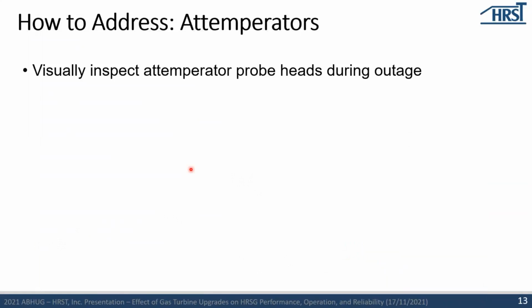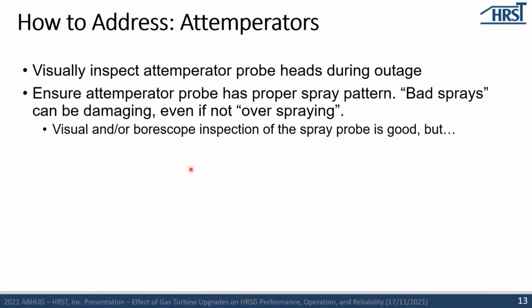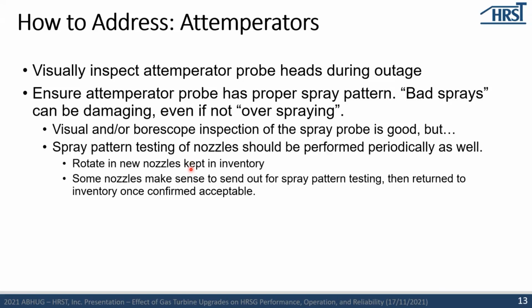So aside from just changing out attemperators, it's always good to perform visual inspections of the attemperator probe heads, because even though you may not be overspraying, that doesn't necessarily mean that there's no issue occurring within the spray water probe itself. If it's stuck open or if it has an improper spray, it could be releasing liquid water into the system that's not evaporating, and this can quench tubes or even cause cracking on the downstream piping as well. So it's important to do spray pattern testing of the nozzles periodically. You can rotate your nozzles in and out of inventory, so you always have a stock of good refurbished nozzles. And then you can plan to send out the other ones for testing and be returned for the next outage.